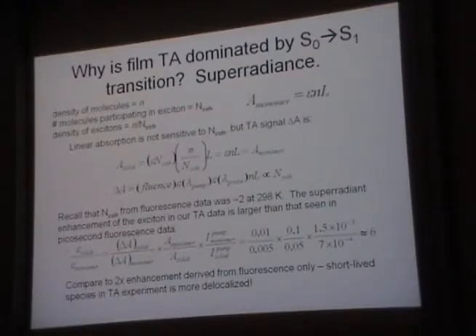And it turns out that if you do the absorption, it doesn't depend on N coherence. It turns out it cancels out, right? You have a lower density because they're all ganging up, but then you have a higher epsilon because they're all ganging up, and the N coherence and the N coherence cancel out. But if you have delta A, you're doing a pump probe measurement, you can do that math, and you find out that N coherence does not cancel out. That's true for any nonlinear measurement, that includes fluorescence, technically. Any nonlinear measurement is going to be, the amplitude of that measurement is going to be sensitive to the coherence length, and then roughly as the order of the nonlinear measurement.